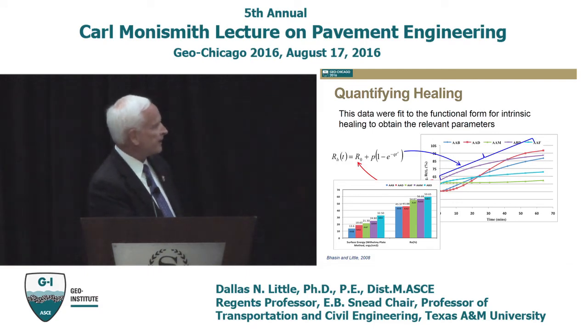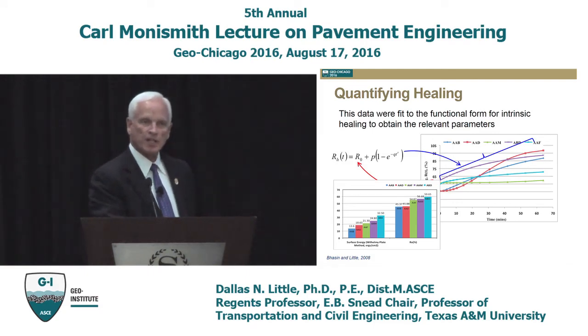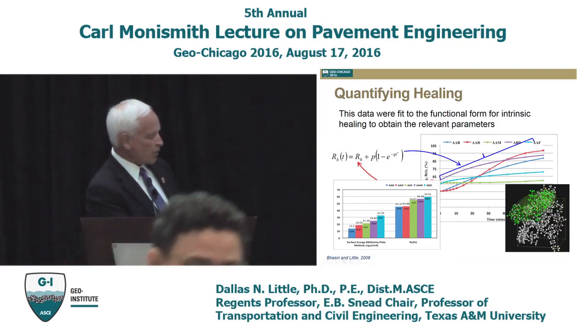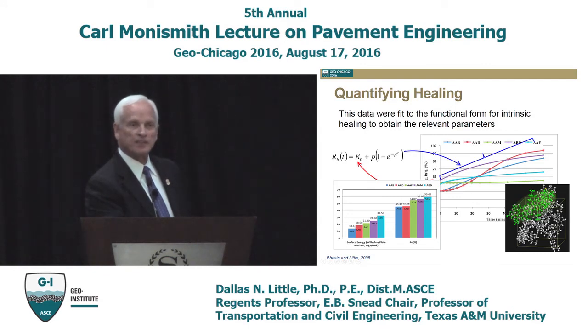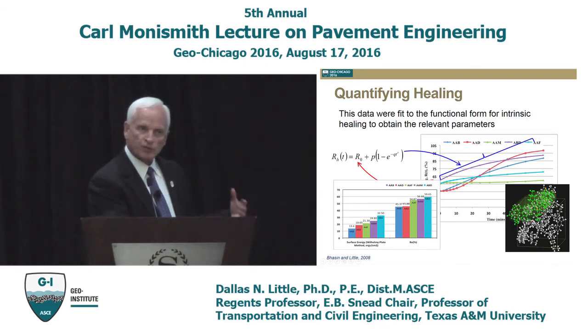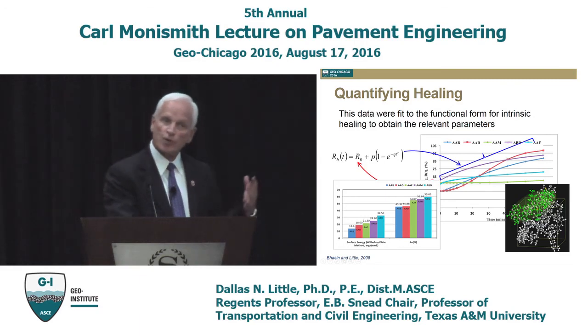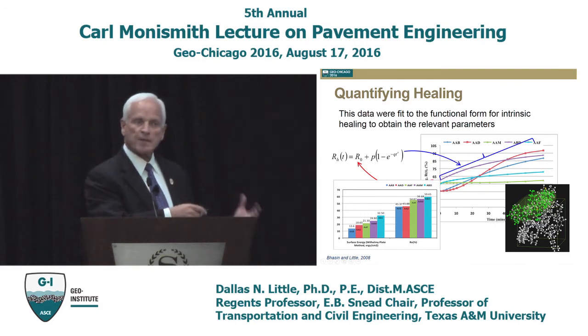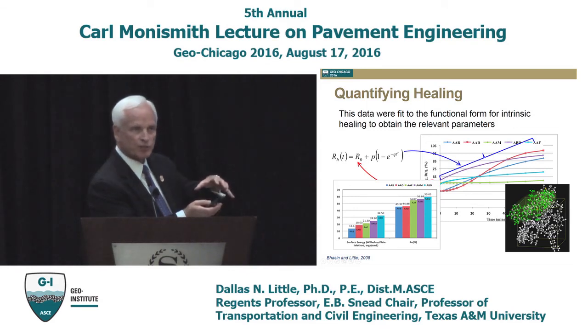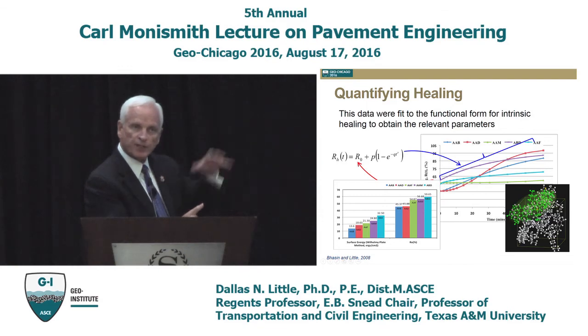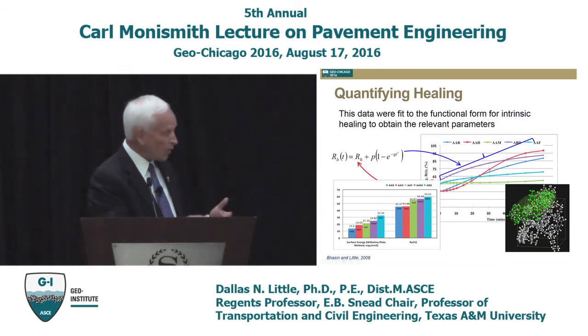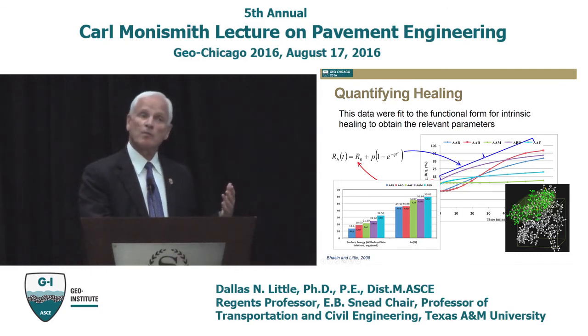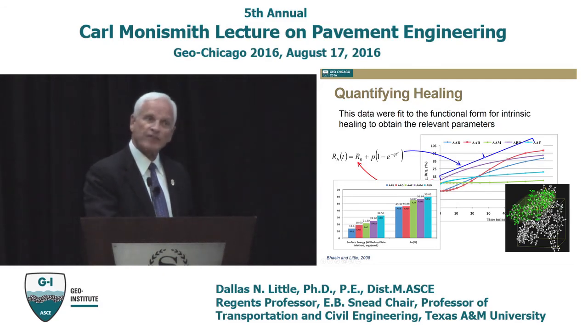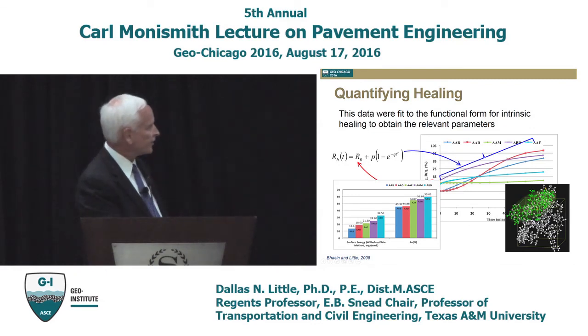Then we went one other step, and we used some dynamic simulation, molecular simulation, to evaluate how mobile the asphalt is. So we looked at different models of asphalt with different components of saturates and aromatics and asphaltenes and so forth, different polar components, to try to model mobility. And how mobile is the asphalt as the crack closes to minimize free energy across that crack face. And what we found was not surprising, and that is the more mobile the molecular structures, the greater the healing, and the faster the healing. So that gave us a lot of confidence.